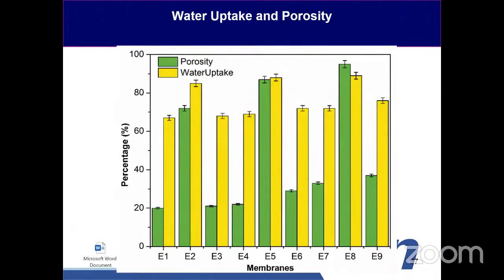Later on, we checked the prepared membranes' porosity and water uptake. This is an important parameter for any membrane when we go with water-based applications. Porosity will directly give us the water permeation through the membrane, and the water uptake. As you can clearly see, in all these samples, this is 20% incorporated, this is 30% incorporated, this is 40% incorporated, right? With the different electrospinning times, the 30% incorporated sample gave us higher porosity and higher water uptake, because the fiber size is quite less in case of 30% incorporated LTC.